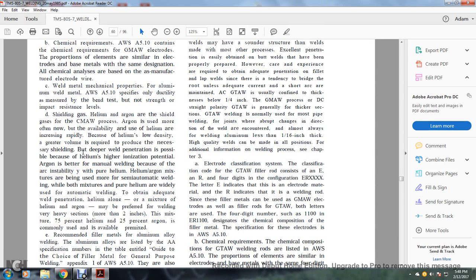Shielding gas for aluminum: argon shielding gas is most often used for gas metal arc welding because of its availability. Helium is used less often because its low density requires a high flow rate to produce the necessary shielding, but it produces deeper penetration because of its higher ionization potential. Argon is better for manual welding because of the arc instability of pure helium.